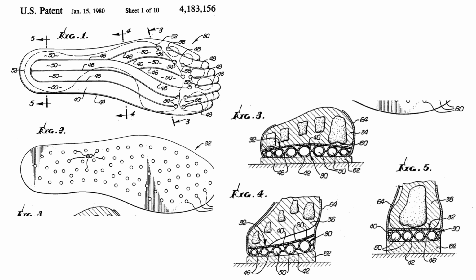The layers 40-42 are welded to one another at their peripheries 44 to form a sealed barrier member 30, which is inflated by a fluid to cause the intercommunicating chambers 50 to assume their tubular form. The material of the inflated insole 30 and the fluid which fills the chambers 50 are preferably selected so that the fluid will not diffuse significantly through the walls of the insole 30 over an extended period of time, e.g., several years. The insole preferably remains inflated to support a wearer's foot 52 over a period of time longer than the life of the article of footwear in which the insole is incorporated.